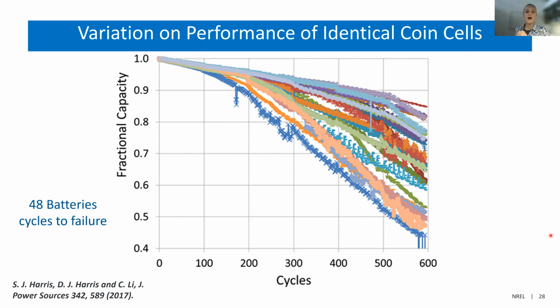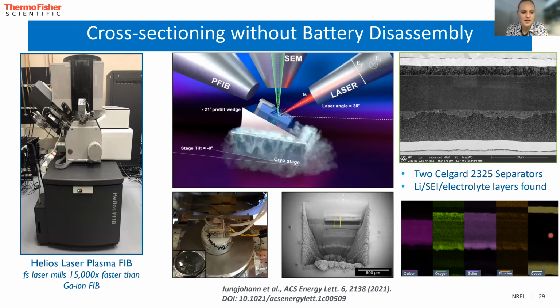Our collaboration with Thermo Fisher Scientific and the University of Oregon led us to this instrument, which is a femtosecond laser attached to the side of a plasma focused ion beam. The laser comes in here at a 30-degree angle from the side, the plasma FIB is on the other side of the instrument, and from the top down you have the SEM beam to take your images. All these are oblique cross sections through the sample, so they're not exactly perpendicular to the battery stack, but we were at a good enough angle that we could really see all the different layers with clarity.